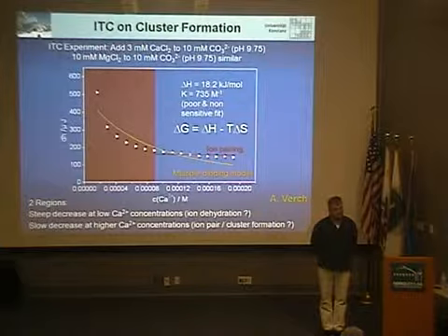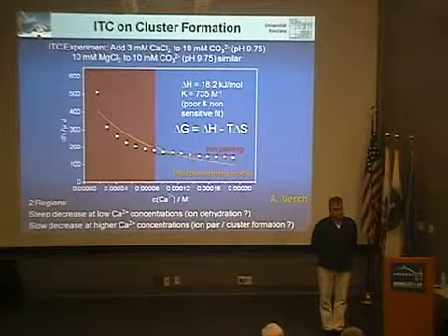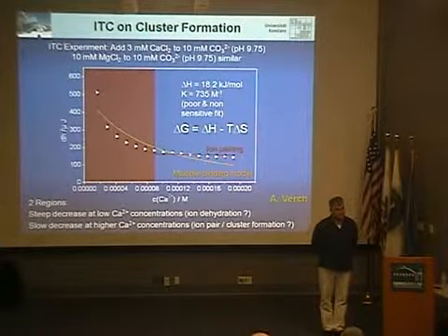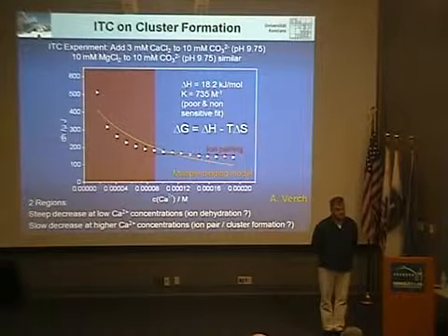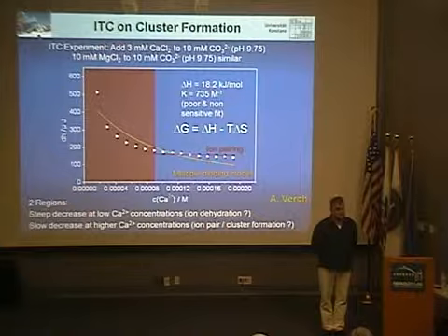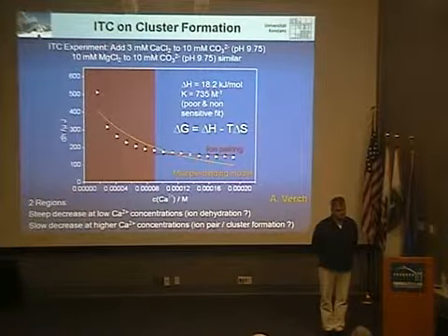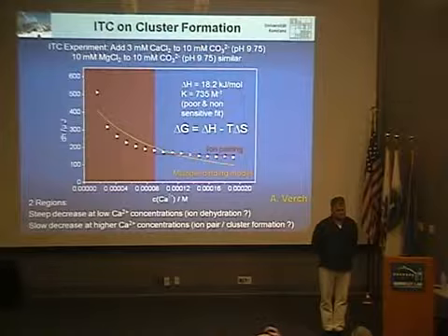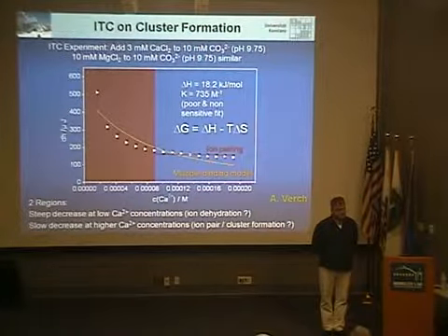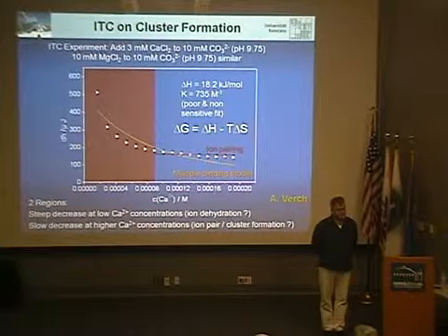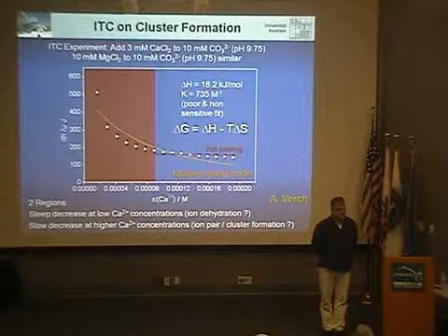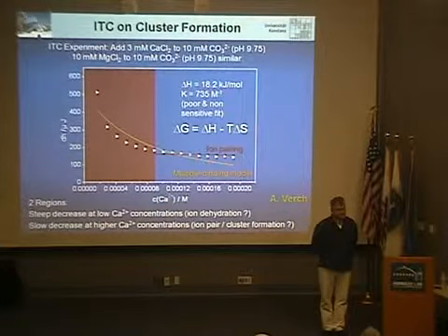I'm glad you brought up this example of clusters that land on a crystal surface and spread to form layers. That's observed in a few protein systems if you go to sufficiently high concentration. Those systems have liquid-liquid separation, and so they're protein-rich droplets. In the inorganic systems, the only example that we've seen is calcium phosphate at very high concentration, where you can start to see these clusters land. But at lower supersaturations, almost all the growth is ion by ion.